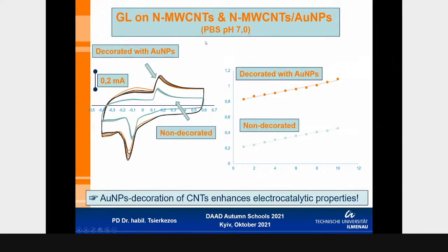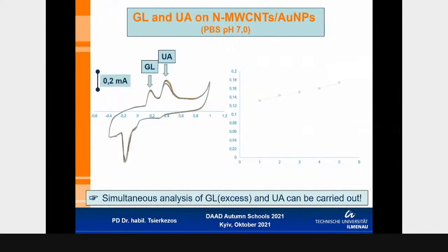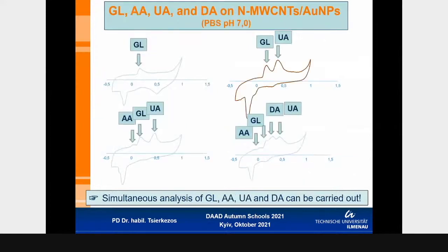I have tried actually to measure a four component redox system by using nitrogen doped carbon nanotubes in the presence of gold nanoparticles, and the results are the following. First, uric acid, various concentrations in the presence of glucose, and in the second step, ascorbic acid. So a third peak has been observed, and then I added dopamine, and I observed a fourth peak. So it's possible somehow to investigate by using this kind of materials a redox system in a single measurement. But these experiments are still in process, so I cannot present some more results. I think important should be also the diameter of the particle in order to separate all of these peaks. But as a first step, I am quite satisfied with this measurement.